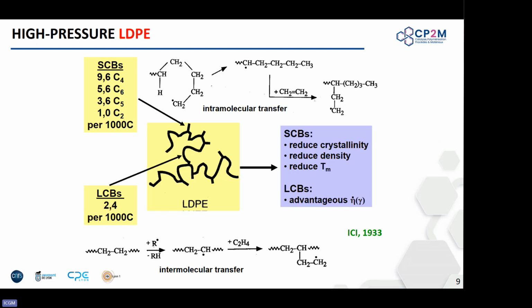1933, ICI, a company, they discovered that if you pressurize ethylene at high temperature, and you have a little bit of, let's say, peroxide impurities, a little bit of oxygen in your reactor, you will end up with low density polyethylene. Low density polyethylene is a little bit particular, so it's a radical process. There is no metal involved, okay? There could be, but it's not necessary here.